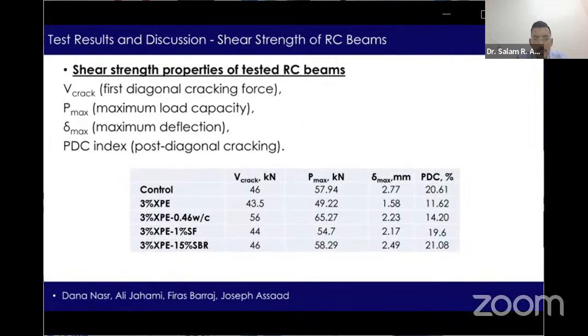So in addition to the values of Pmax representing the maximum load capacity and delta max representing the corresponding maximum deflection, the table in this slide summarizes the values for the tested reinforced concrete beams corresponding to V crack, which represents the first diagonal cracking load, and PDC, or post-diagonal cracking index, that is used to quantify the maximum beam resistance after the formation of the first diagonal crack. So let's discuss these results together.